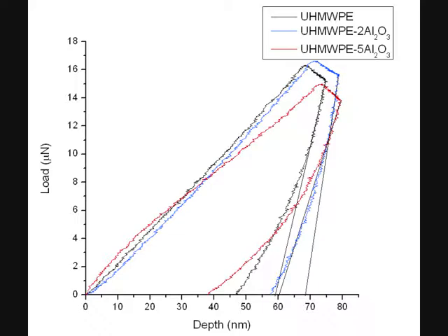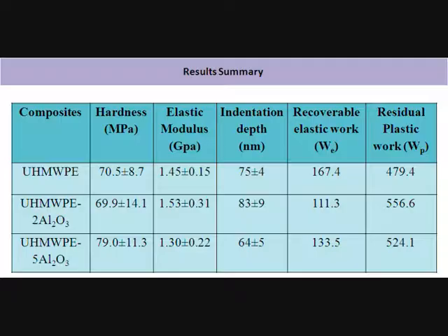Here we can clearly see that the residual depth is least in the case of ultra high molecular weight polyethylene with 5% aluminium oxide, while it is greatest in the case of ultra high molecular weight polyethylene with 2% aluminium oxide. On the basis of these nano indentation curves, we can infer that the addition of 5% aluminium oxide increases the hardness of the material up to 79 MPa, and the minimum indentation depth is around 64 nanometers.